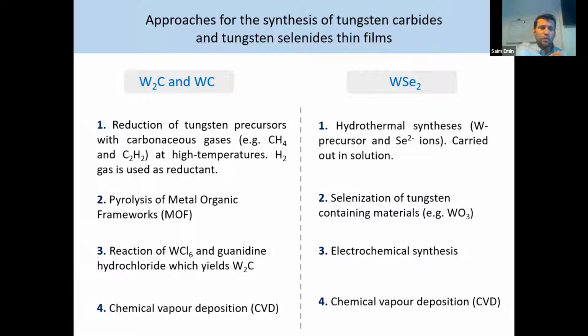The approaches used for the synthesis of carbides are reduction of tungsten precursors with carbonaceous gases, pyrolysis of metal organic frameworks, reaction of some tungsten salt with, let's say, molecules like guanidine hydrochloride, and chemical vapor deposition. Same for selenides. Selenides can be produced hydrothermally. Hydrothermal synthesis means we need a precursor for the metal ion and for selenium ions. Other routes are selenization of tungsten-containing materials like tungsten oxides, electrochemical synthesis, and CVD approaches.